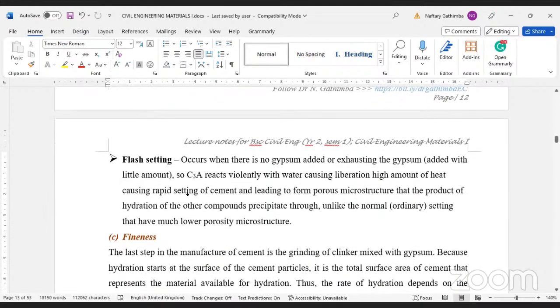And now to differentiate, because I've already mentioned it, we said in flash setting there is no gypsum, but in false setting gypsum is there. In flash setting, there is a chemical reaction that occurs. Tricalcium aluminate reacts violently, releasing a large amount of heat. And this will cause rapid setting of cement. The result of this is that you will end up having a porous microstructure. I know at this stage we are not talking about microstructure, but what we are saying is that you are going to have honeycombing in your cement paste with some pores. It's a requirement for you to get good strength or high strength concrete or cement paste that it needs to be dense. Dense substances have high strength.